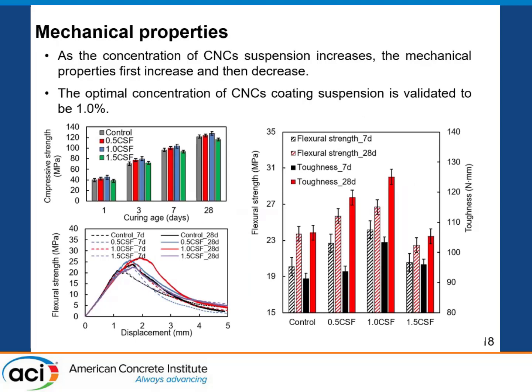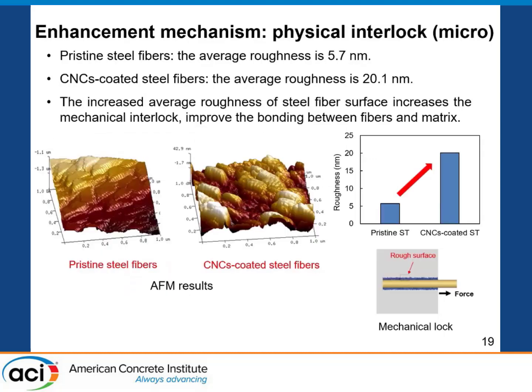The good part is that when we use 1% CNCs to treat the surface of the steel fibers, we show a good improvement in the compressive strength. And the better thing is we show a significant improvement in flexural strength and also the fracture toughness. But when it is increased to 1.5% for the CNC concentration, there's a significant reduction. So we figured out the enhancement mechanisms when we use 1% or less CNCs for treatment.